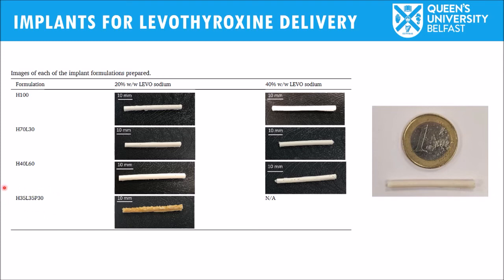We know that the incorporation of this hydrophilic polymer into the matrix can alter the release profile. In this case you can see that all the implants look whitish gray, a color between white and gray. Here you have an implant beside a euro coin to see the dimensions of these rods. Basically, what we observed as soon as we prepared implants including polyethylene glycol in the formulation is that the color was completely different. So we anticipated there was a degradation there.